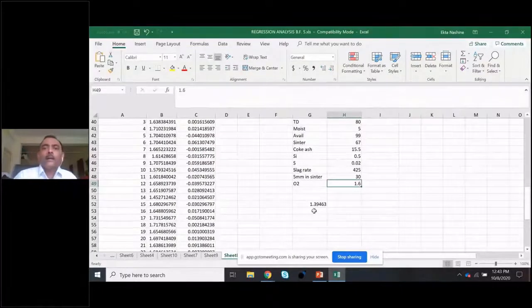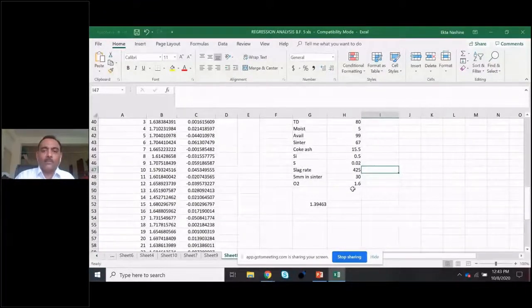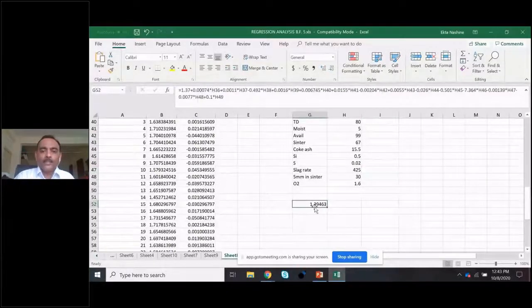Moisture in the raw material is 5%. Availability time for the furnace operation is 99%. Sinter percent in the charge, meaning iron ore and sinter, which is my iron bearing material, in which sinter is 67%. Coke ash is 15.5. Silicon in my hot metal is 0.5. Sulfur is 0.02, because of undesirable oxides inside the raw material. My slag rate is coming 425. Fines of 5 millimeter in sinter is 30. I want plus 5 more, and I am able to give only 1.6% of oxygen. So by that formula, I am able to produce 1.39463 tons per meter cube per day. This is the productivity.